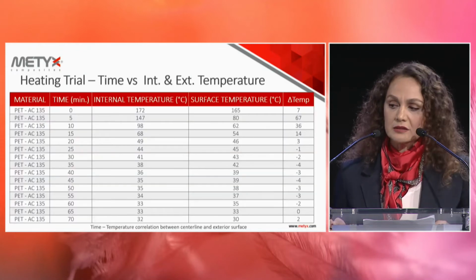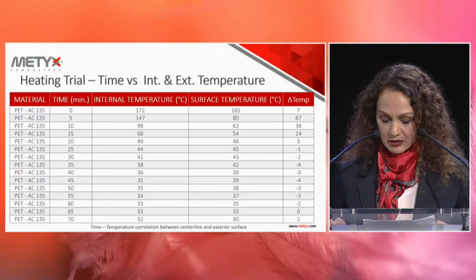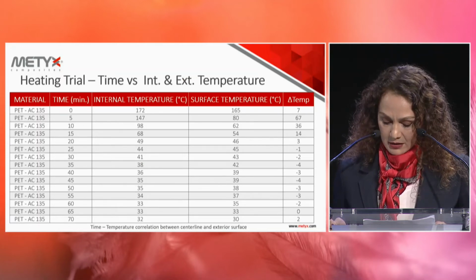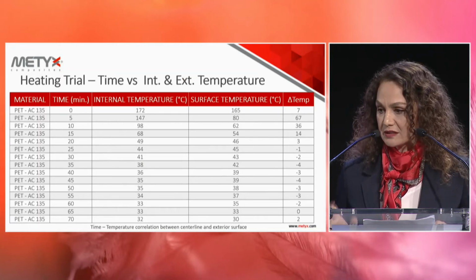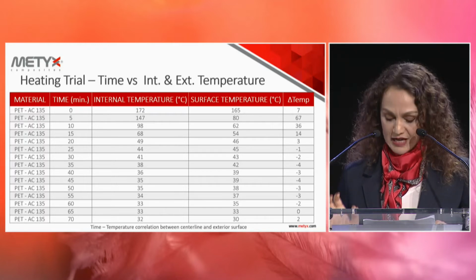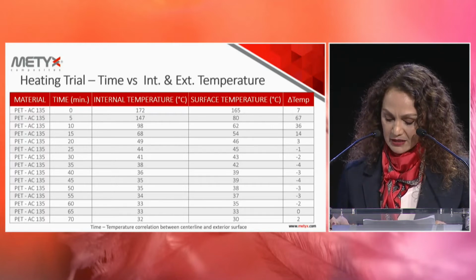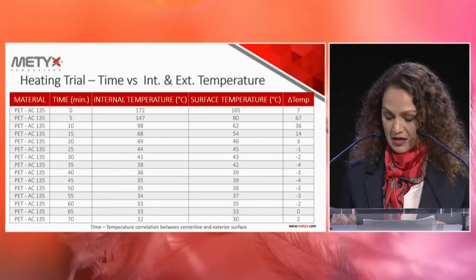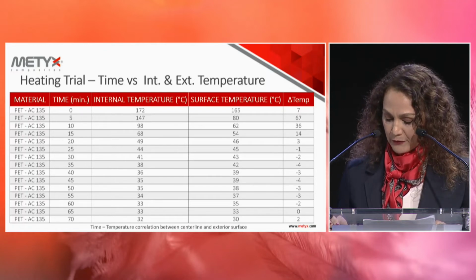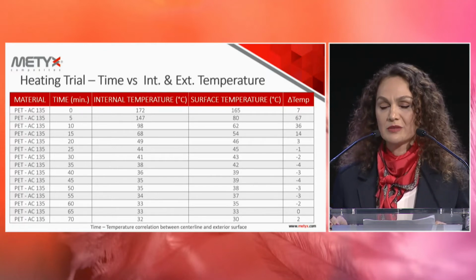So we compared the two temperature changes here. If we look at the differences, it started with high differences in the first 10 minutes. Looking at the result, we can say that, again, from 0 to 10 minutes, we have enough time to form this core in a secure way. It's going to retain its shape.